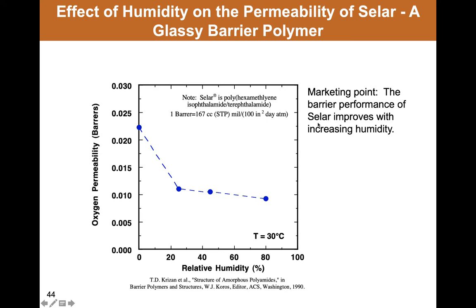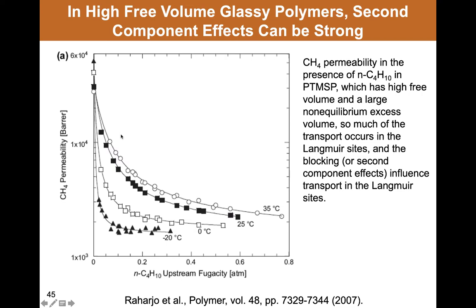These second component effects can actually be quite large. In very open materials like poly-1-trimethylsilylpropyne, which have a large free volume and therefore very high Langmuir capacity, as the content, in this case the partial pressure, of butane increases, it really chokes the flow of methane by more than an order of magnitude at low temperature, where you get very strong sorption of butane, and that really blocks the flow of methane through this material.